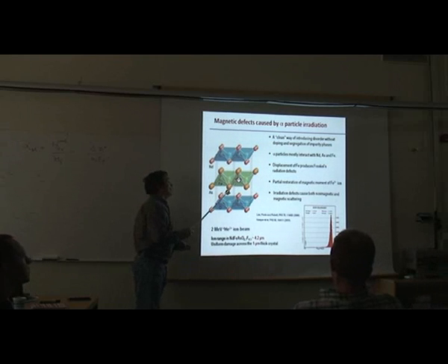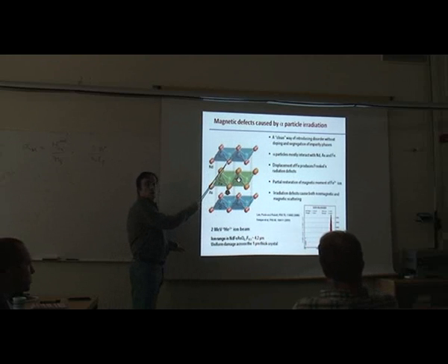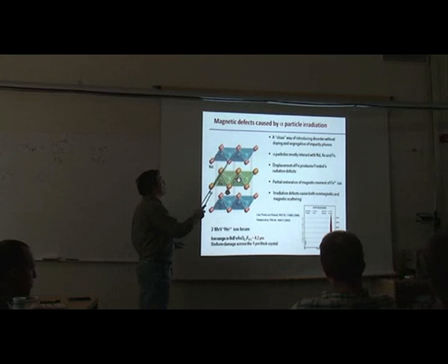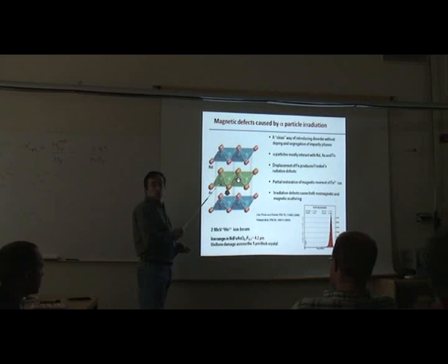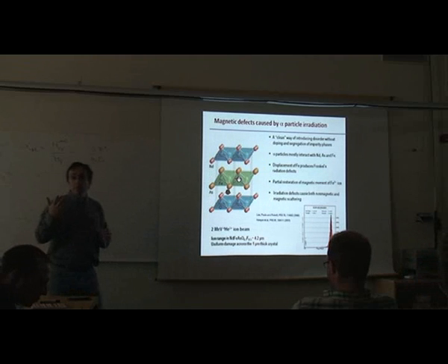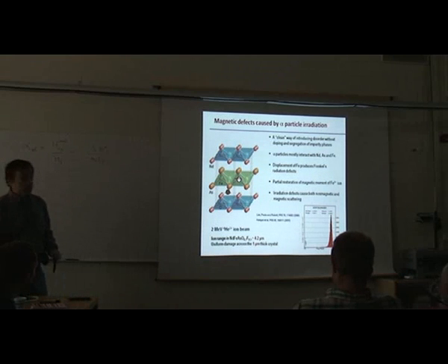So iron has a moment, neodymium has a moment. We can also knock the neodymium out of its place and put it somewhere here. The result will be the same. Neodymium has a magnetic moment even in the superconducting state. So you basically bring magnetic impurities to the plane which superconducts. So in the end, we introduce magnetic disorder by radiation, in addition to the conventional non-magnetic disorder.